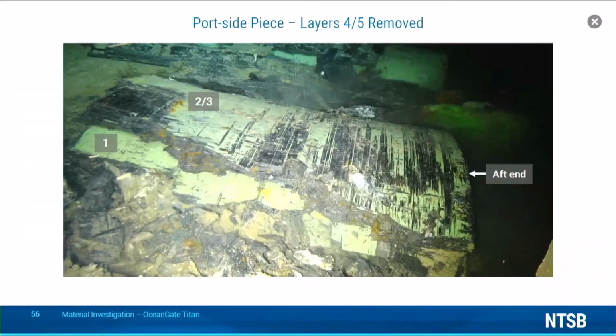The delamination between the middle shell and the outer shell shows a more complex separation pattern. For the piece that was located on the port side, shown on the left, we can see the green adhesive at the top of layer 3, consistent with separation within the adhesive. Looking at this same piece, with the outer shell removed, we see that toward the aft end, there's a mixed region where some of the separation took place within the adhesive and some within the adjoining composite layer. At the forward end, there's also a square patch of composite material still attached to the surface.